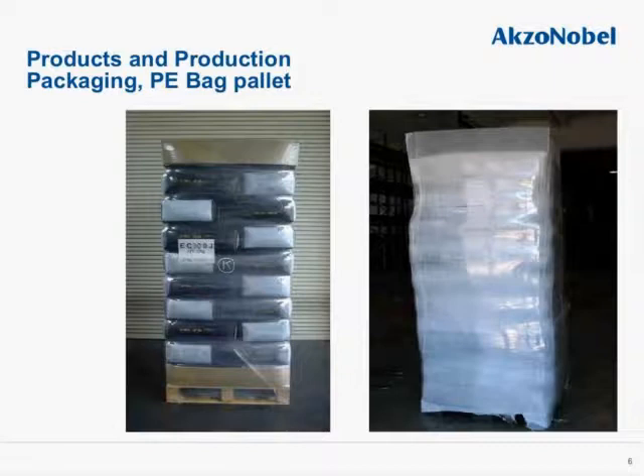Ketjenblack EC-300J and Ketjenblack EC-600JD come in a plastic bag. Ketjenblack EC-300J is packaged in 10 kilos in a bag, and EC-600JD is 8 kilos in the polyethylene bag. We recommend that the product be dispersed into the end compound by opening the bag and having the Ketjenblack free-flowing into the mixer, whichever mixing equipment it is, or by tossing the bag entirely in the mixer, as there's a vent on each bag that is a mix of various polymers for ensuring breathability of the bag.